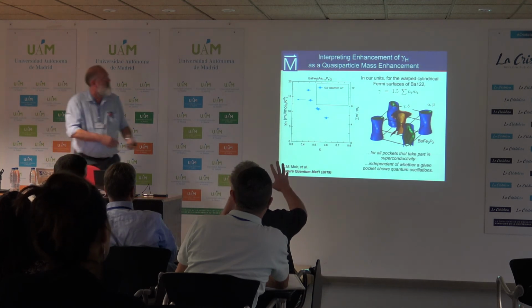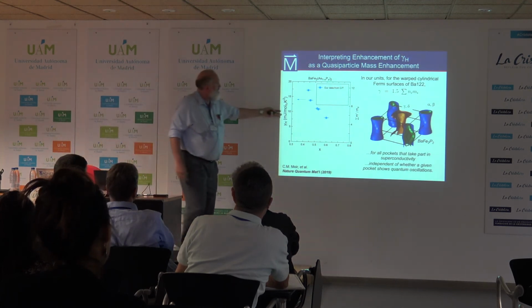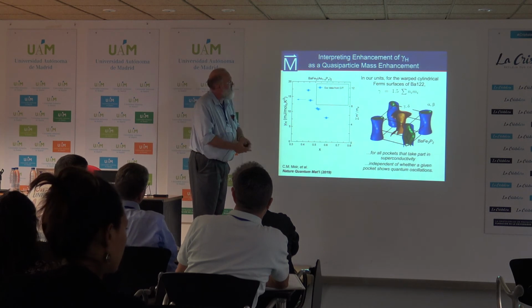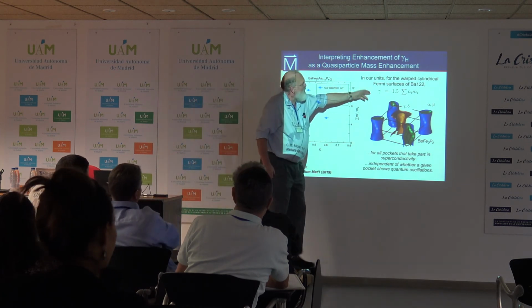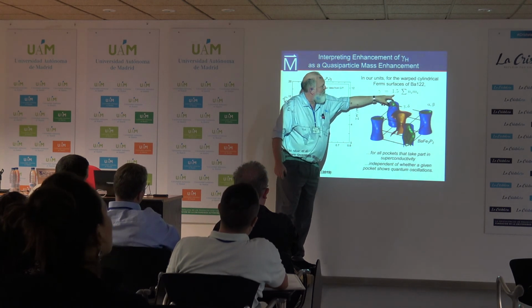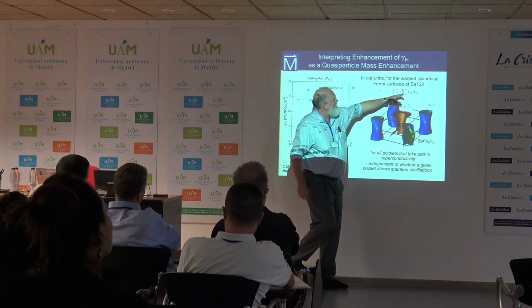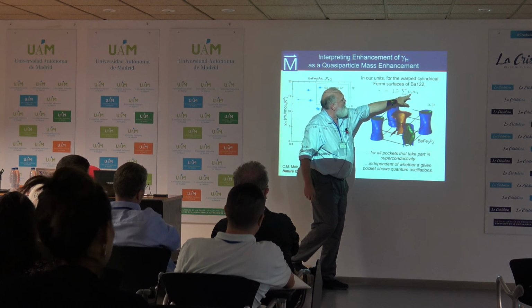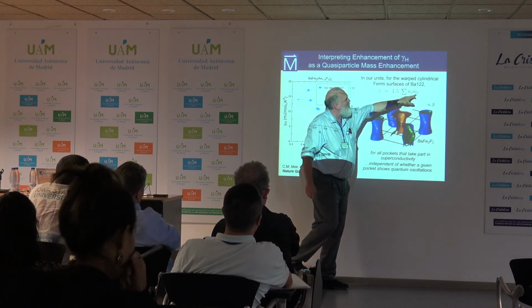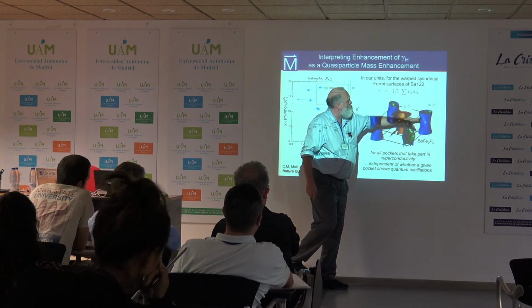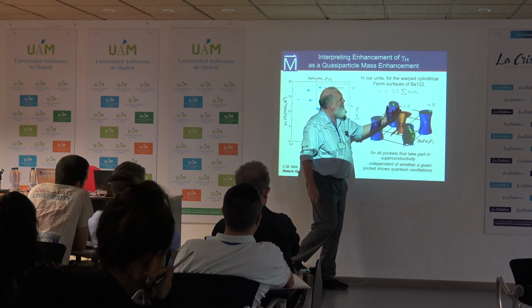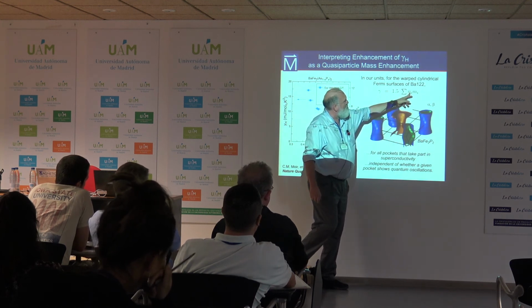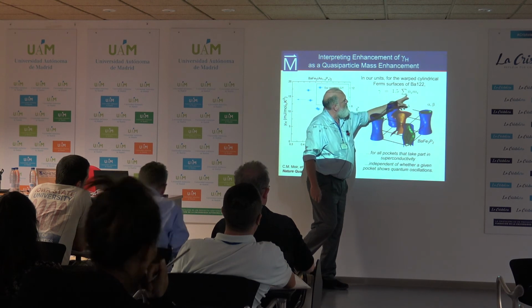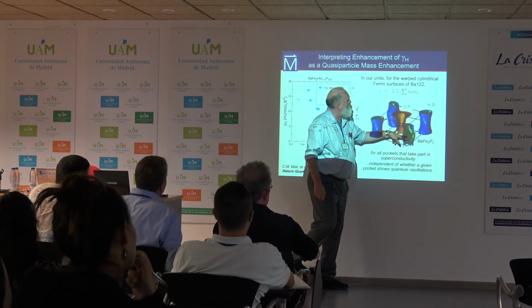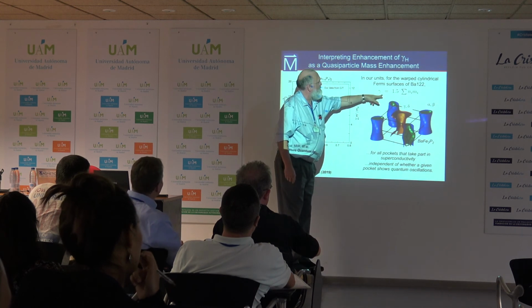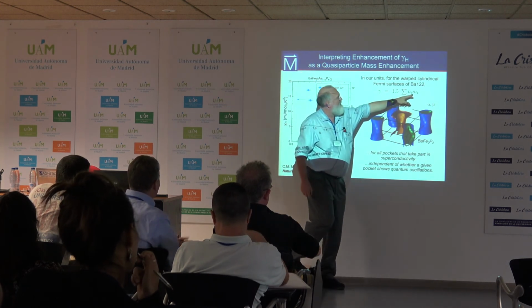So we can convert these numbers of specific heat in a quasi-2-dimensional system by a very simple formula that has a prefactor out front that has the area of the Brillouin zone in it, and then a sum of the number of pockets of type i times the mass of those pockets. Well, in this case, you've got 4 different pockets, but you've only got 1 pocket of each one, so your n sub i's are always equal to 1, and so you're measuring the sum of the masses of these 4 pockets in converting your electronic specific heat to mass.